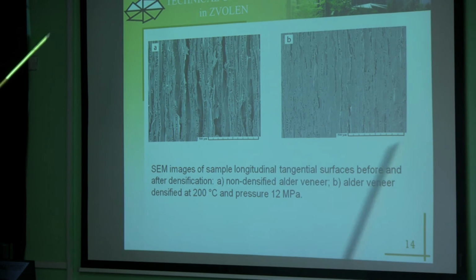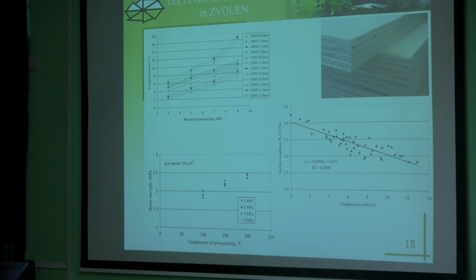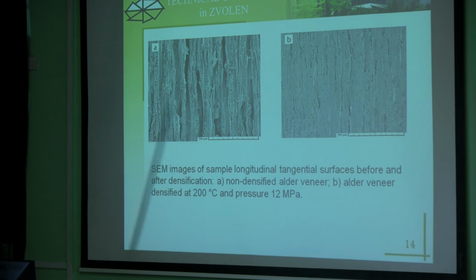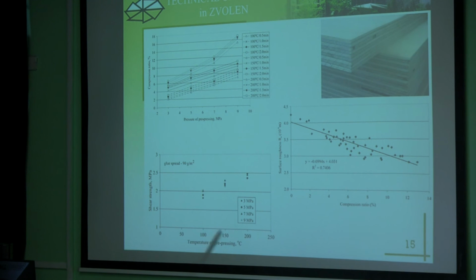If the surface is closed like this, the glue spread was lowered to amount of 90 grams per square meter. Generally is used the glue spread about 150 for such prepared surface. So we can see that prepressed veneer at 200 Celsius, and higher pressure has much higher strength properties than prepressed veneer at 100 Celsius.